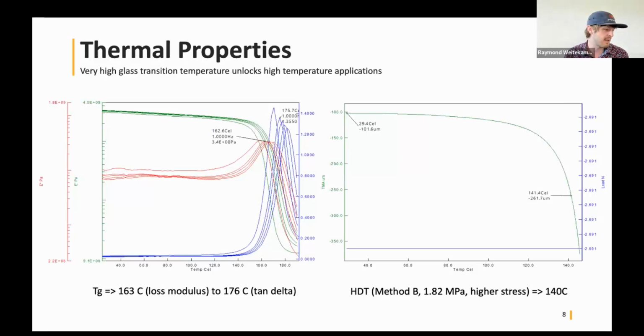And one thing that I'll add, that I don't have a specific slide on, is that we have almost no moisture absorption. So not only is there really high chemical resistance, but because of this toughness, working temperature, and no moisture absorption, this is definitely better than printed nylons, especially sintered powdered nylons. In many cases, we can be better than injection molded nylons, because a lot of the challenges with some of those materials is related to the fact that they just suck up water, and some of these nylons can have 1 or 2% water by weight.